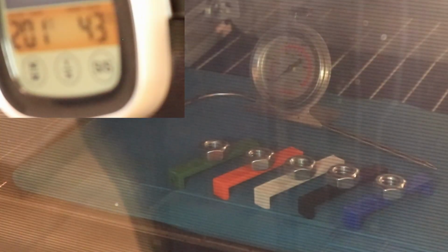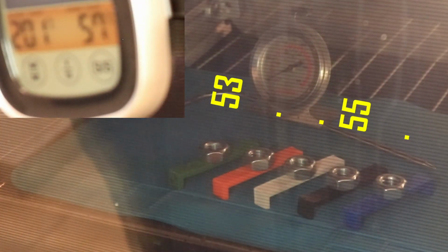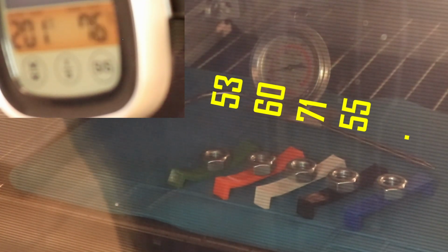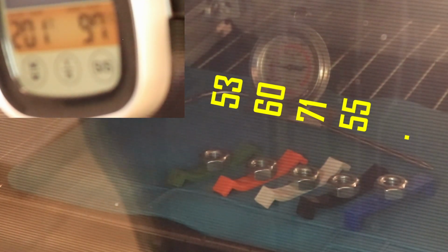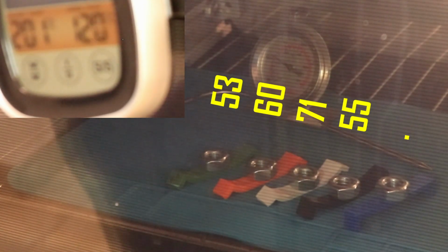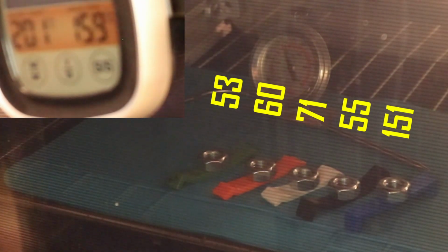PLA Advanced started with deformation somewhere between PLA and PETG, but later it slowed down and deformed after ABS test object. On Engineering PLA I noticed the deformation only at approximately 150 degrees Celsius. That was very impressive. The temperature is 173 degrees Celsius, and I will stop the experiment here.